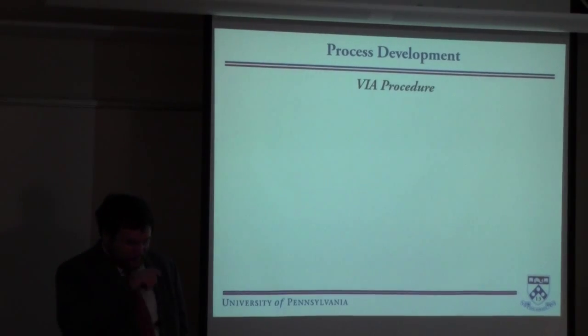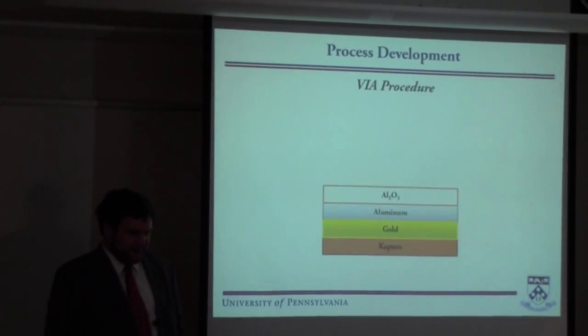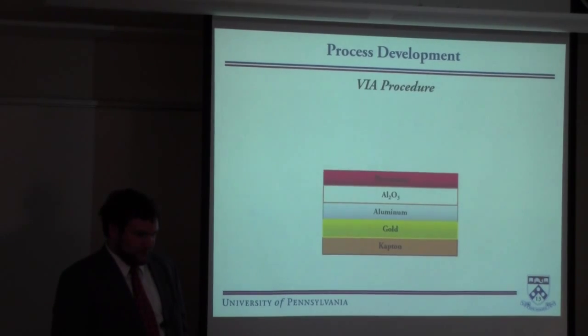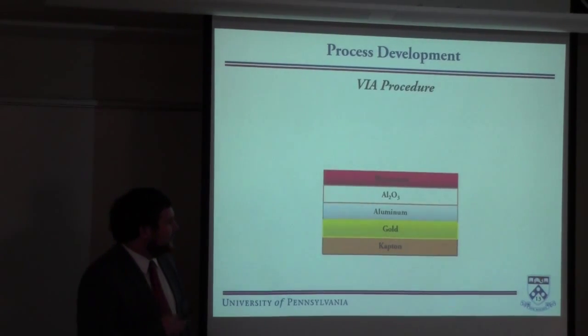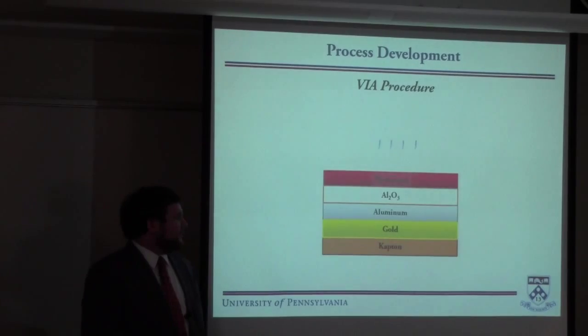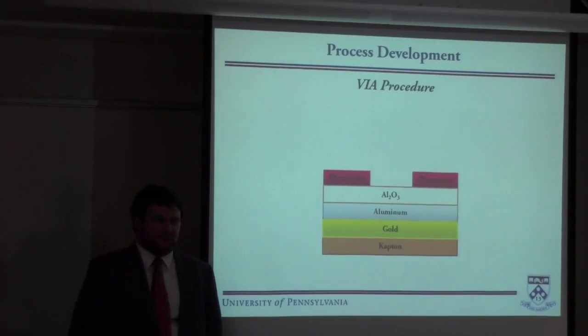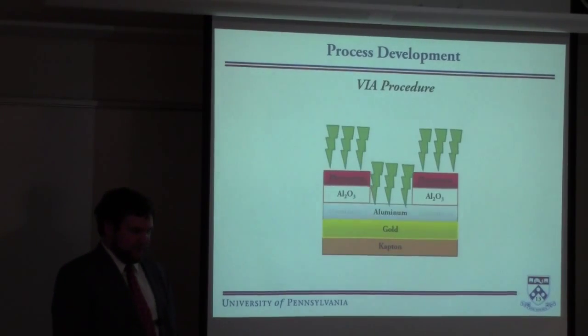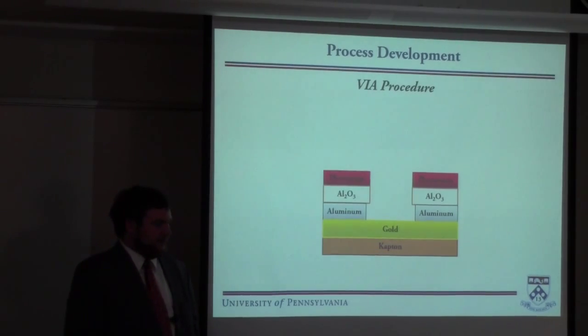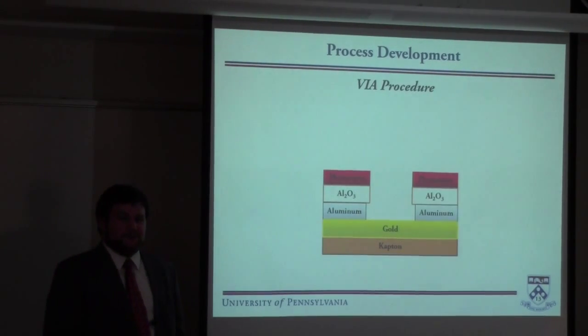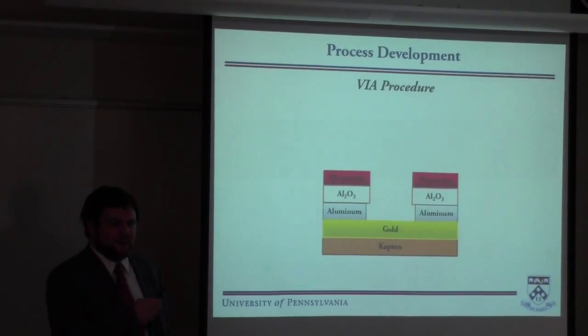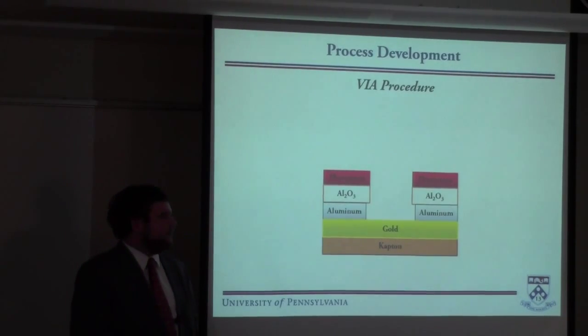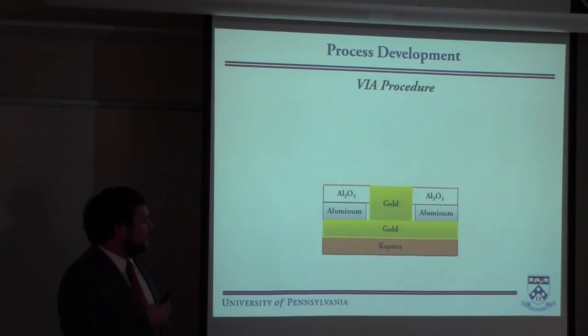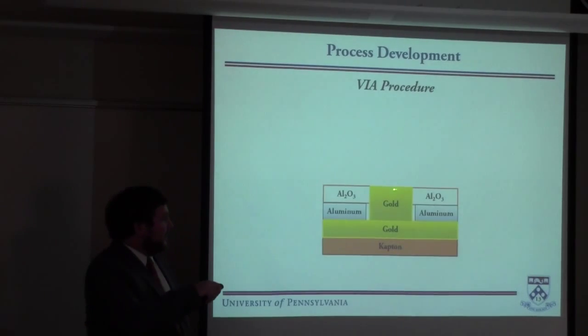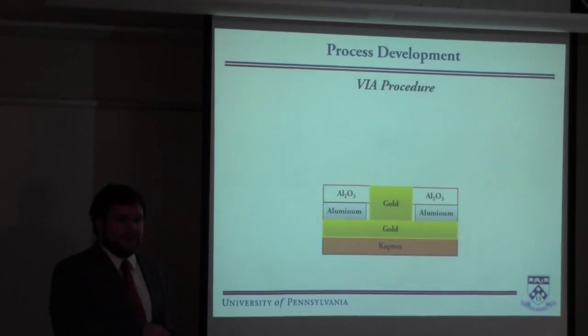So the solution to this came with many, many, many iterations, but it came with a suggestion of putting gold under the aluminum, so that we can actually etch through the Al2O3 and through the aluminum, but the chlorine plasma won't etch the gold. The gold's a noble metal. It'll form a thin layer on top, but it's not going to do very much to the gold. And then we can refill that with gold, and now we have a conduction path through the Al2O3 layer to the gate.